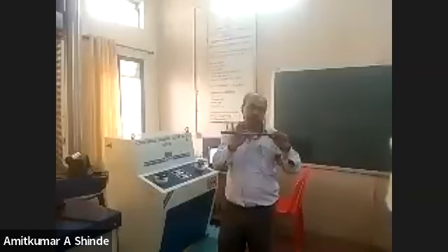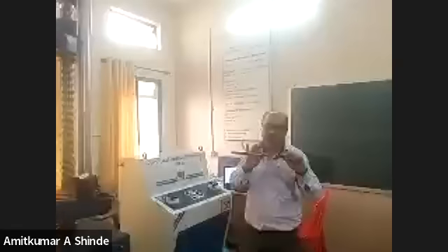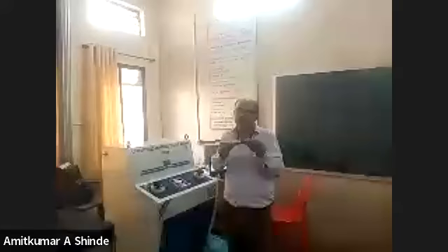So I will take this diameter as 10 mm. So pi by 4 into d square, where d is 10, means 10 into 10 into pi divided by 4. So we get the cross-section area. Then you take the root of that cross-section area, into 5.65 as per Indian standard. You will get this gauge length. So this is called gauge length, and this diameter is called gauge diameter.